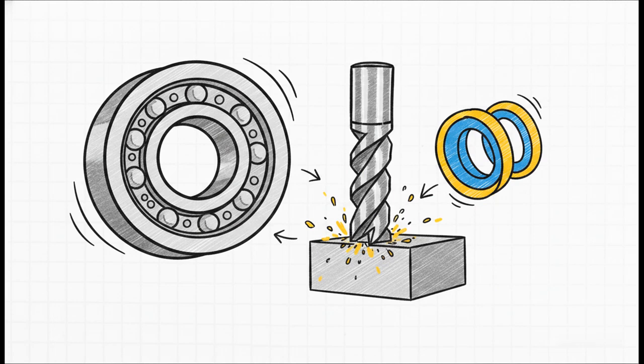That's where those elongated beta grains we talked about earlier step in to prevent catastrophic material failure under friction. It's also quickly becoming the absolute gold standard for EV motor insulation and semiconductor plasma equipment, where parts have to resist wear while providing perfect electrical isolation at super high temperatures.